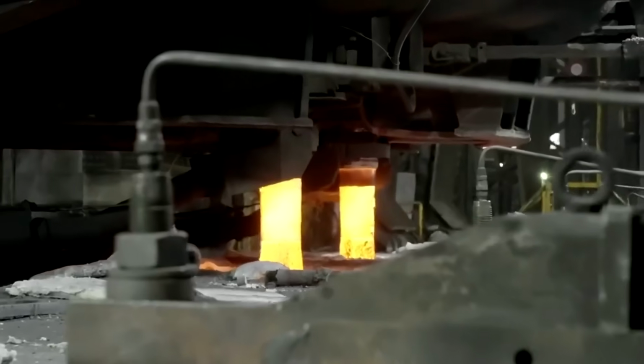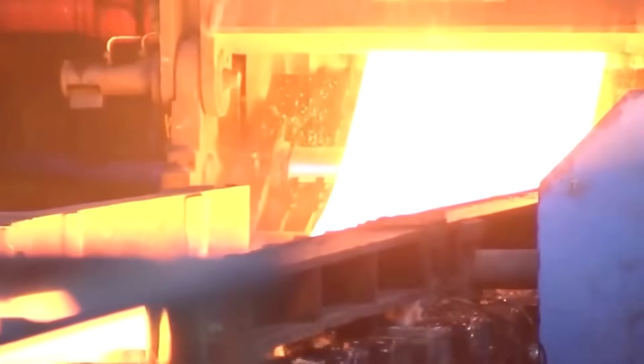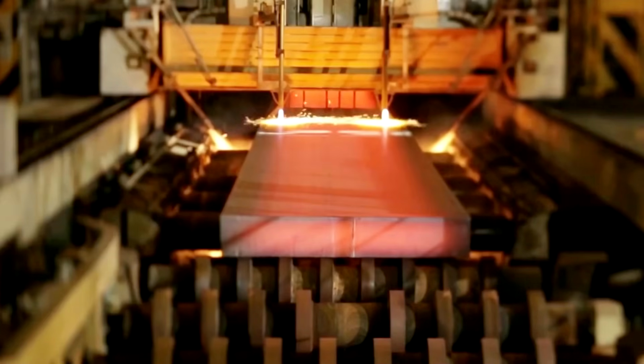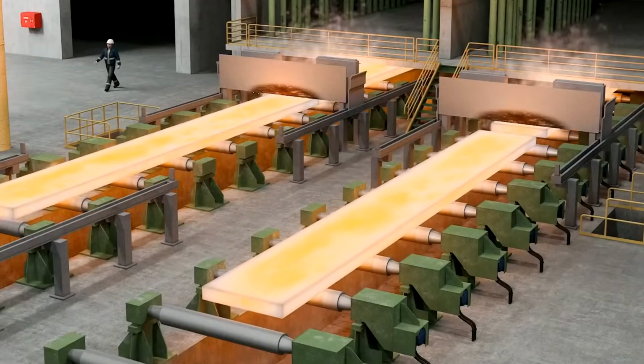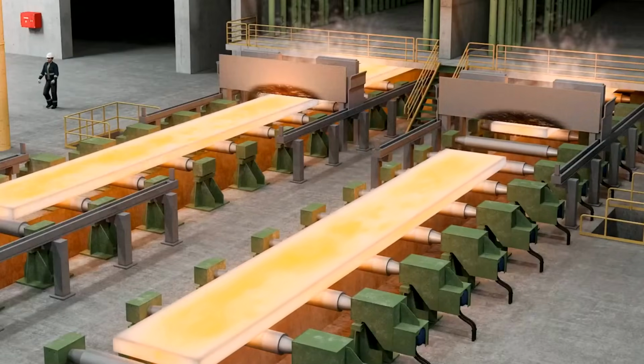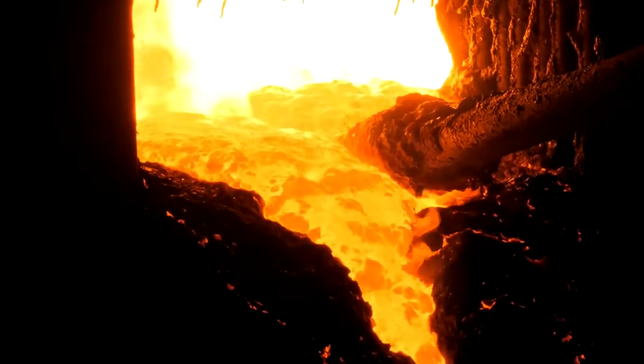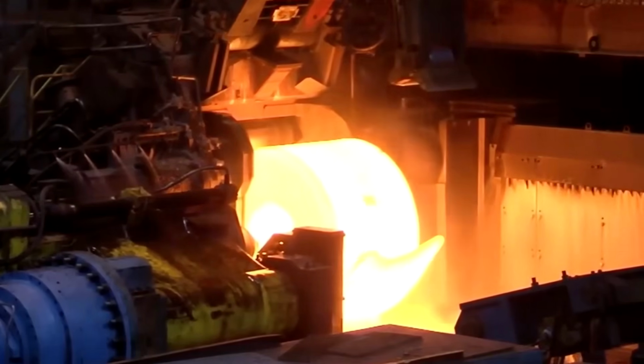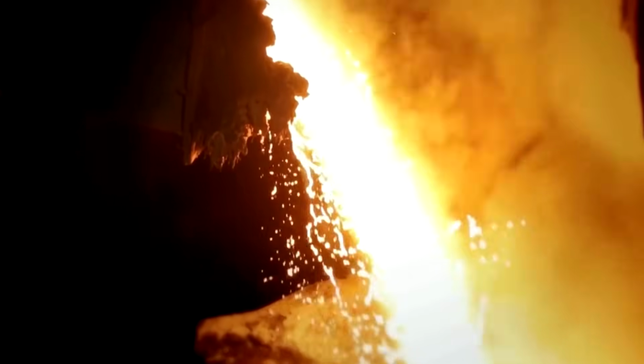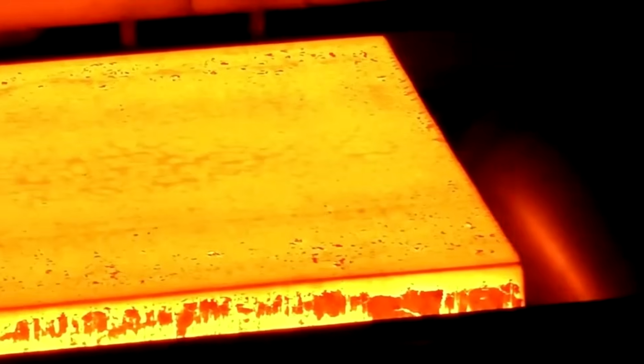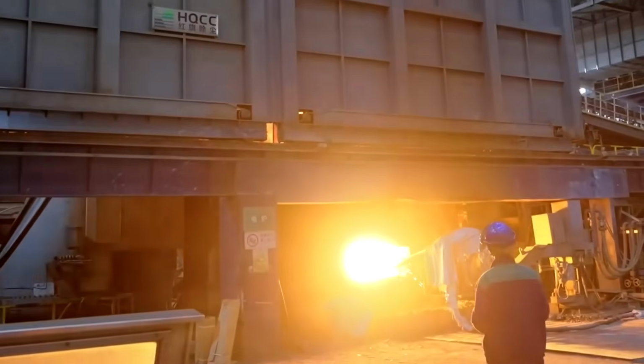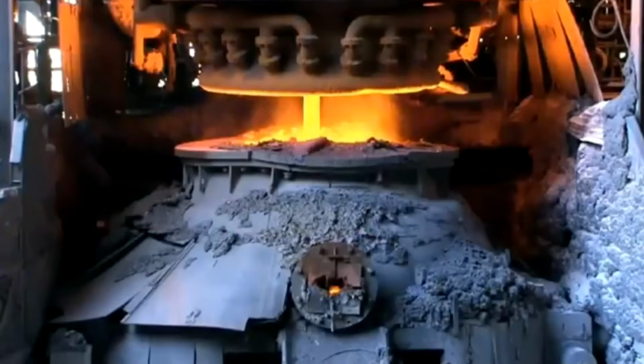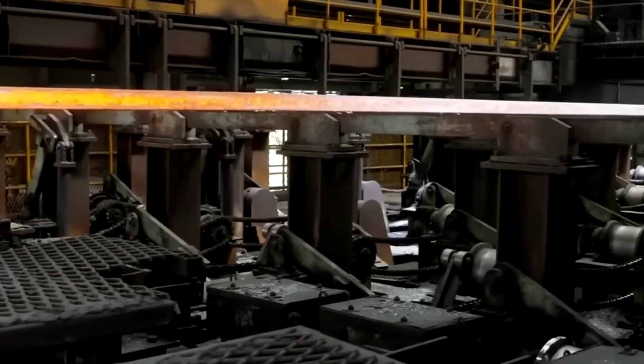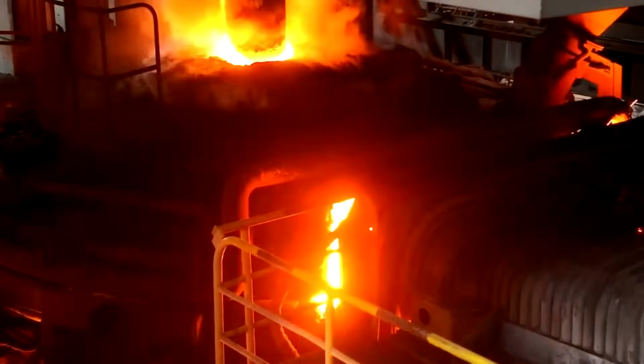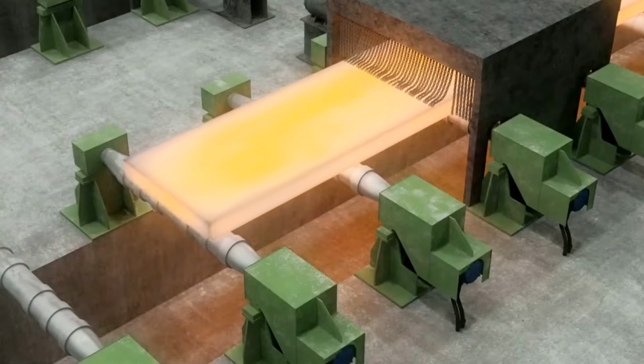The metal is transferred directly to the hot rolling line to undergo a massive structural transformation. Reheating units bring the billets to approximately 2,300 degrees Fahrenheit to soften the crystalline structure of the metal. This high temperature makes the heavy blocks easier to shape under the pressure of industrial machinery. The billets pass sequentially through a series of massive rolling mills that stretch the material. Each pass compresses the steel further, making the billet thinner and longer, while it moves progressively closer to its final industrial shape. One can notice how the red-hot metal accelerates as its thickness decreases under the force of the rollers.